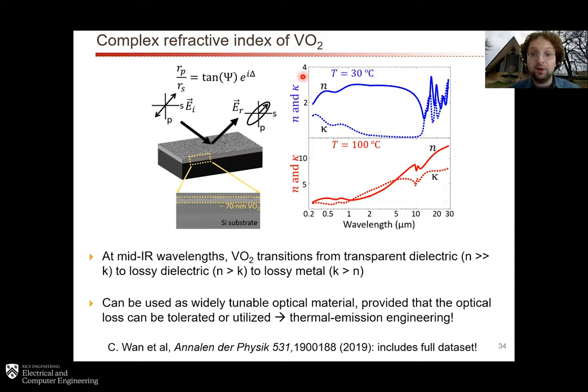So in this case, we're plotting the N and K, the real and imaginary part, before the phase transition and after the phase transition across this whole range. And what you find is that at mid-infrared wavelengths, which is where we're interested in for the thermal emission work, VO2 transitions from being more or less a transparent dielectric to a lossy dielectric, all the way to a very lossy metal.